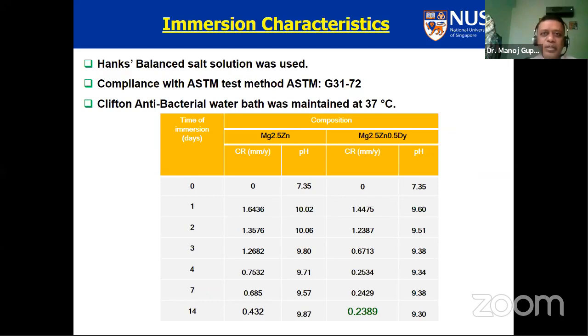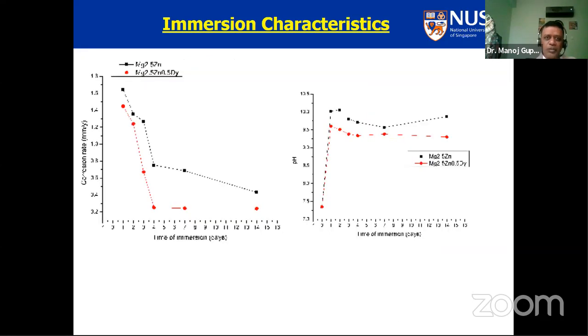And then we did the immersion characteristics in the Hank's balanced solution, and you see that magnesium with 2.5 zinc and 0.5 dysprosium has a very low rate of corrosion. So now we have improved on the mechanical properties and on the immersion characteristics of this material, which is very good. This graph shows the red curve, how much the corrosion rate immediately goes down once they're exposed to the solution for magnesium 2.5 zinc, 0.5 dysprosium, and the pH fluctuations are less compared to magnesium with 2.5 zinc.